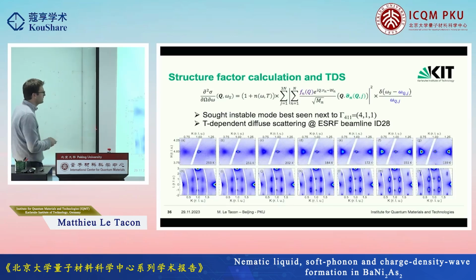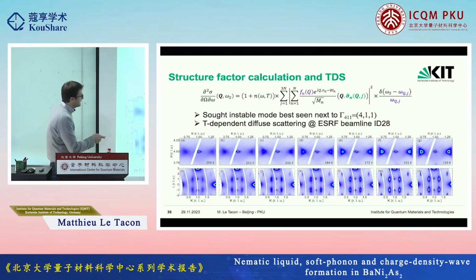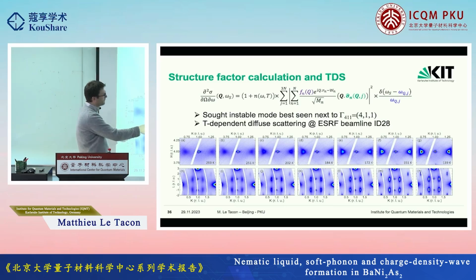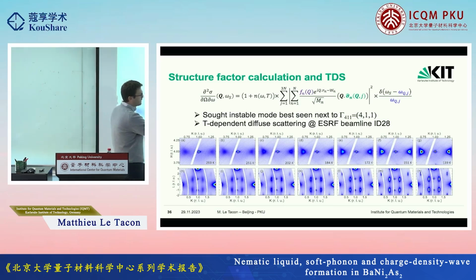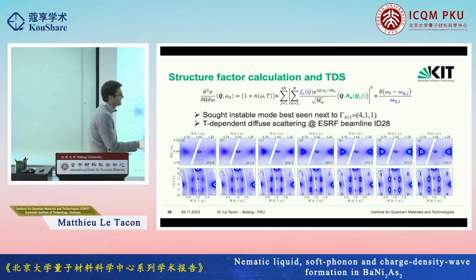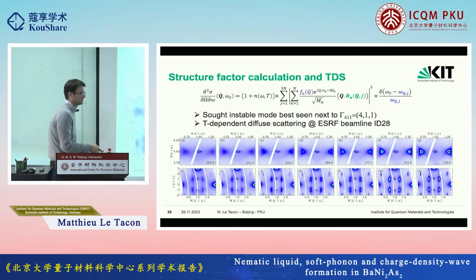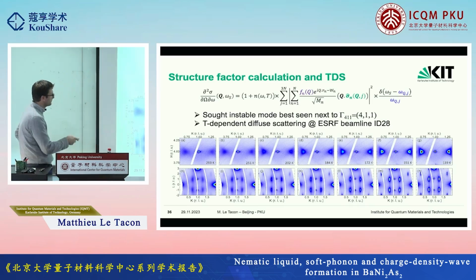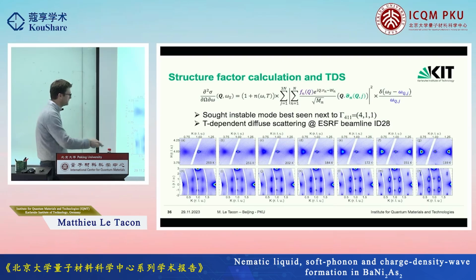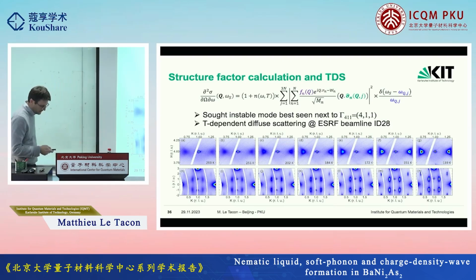So we can look at the diffuse scattering as a function of temperature, and what you see upon cooling is that this diffuse scattering becomes stronger and stronger, and at some point it becomes so strong that it's actually as strong as the Bragg reflection. Okay, and so this is pretty much the region where we start seeing this in the lab machine, and then we can look at it in the plane and perpendicular to the plane.